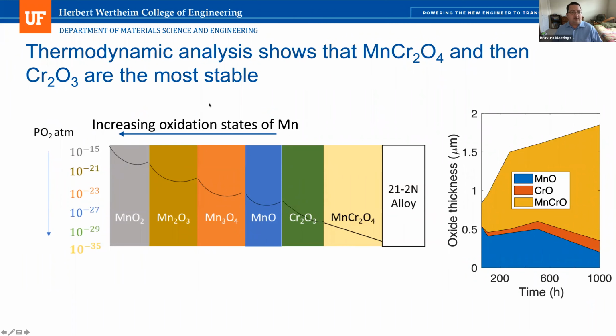So if we look at the oxygen partial pressures of these different types of oxide, manganese oxide, chrome oxide, and the spinel, the most stable oxide is, thermodynamically, going to be the spinel, and then the chrome oxide, and then the manganese oxides, and there's various types, are going to be less stable. And that explains why over time we see the manganese oxide thin and the chrome oxide and the spinel grow.